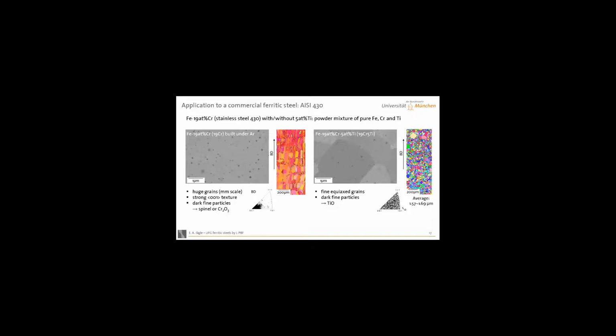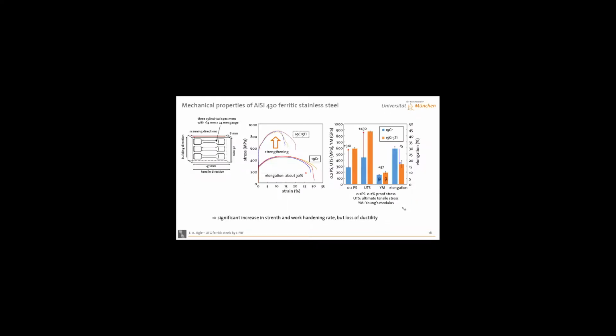You've seen this before. This is the quasi single crystal behavior. And if we add now 5% titanium, the grain refinement in this case comes again from the dirty iron powder. You see the stark difference in microstructures. You see the stark difference in texture. And we now produced blocks of these two different materials, machined tensile test specimens out of them, and looked at the results. And the result is, yes, there's a significant strengthening, quite a lot of strengthening.